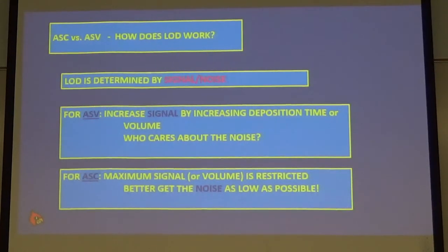Our sample volume has to be fixed, or else we can't follow Faraday's law. So we can't improve our signal by increasing the volume. Well, in fact, one of the things that Kelsey is doing right now is increasing the volume by small degrees. So instead of a 100 micron thick cell, she's making thicker ones. If you double the volume, that should double your signal and should get you from 50 to 25 ppbs.